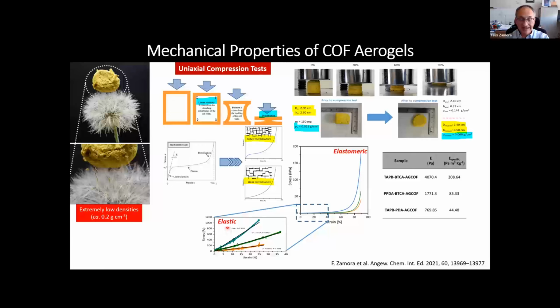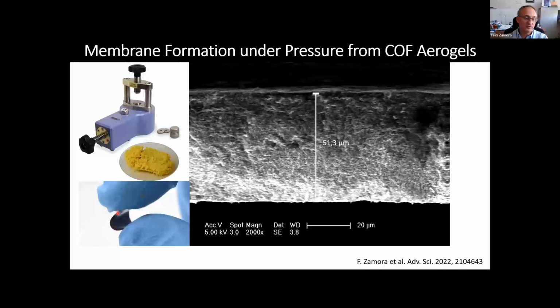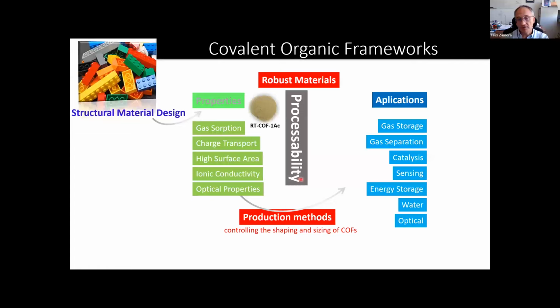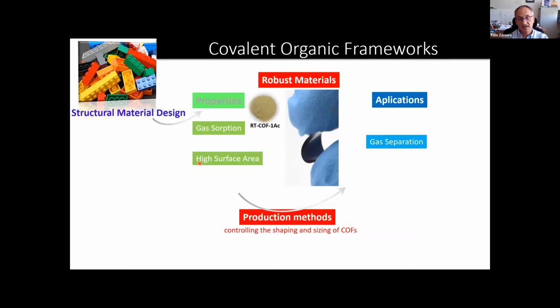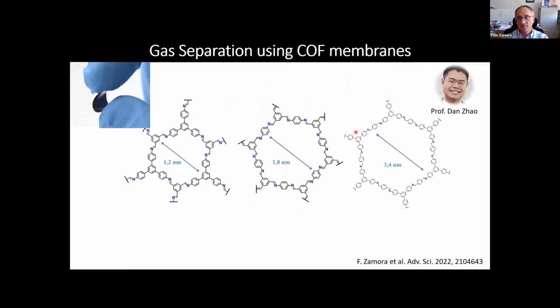The meaning of that is that, of course, the density is enhanced by a factor of three, but you pass from a monolith to a kind of membrane. This is the final material. You enter into a flexible membrane. Okay, and we thought, we have a material, a membrane that shows nice gas sorption, high surface area. Why don't we try to use this membrane for something useful, gas separation, for instance? And with the help of Professor Dan Zhao from National University of Singapore, we produced these three different membranes coming from the compression of the aerogels.